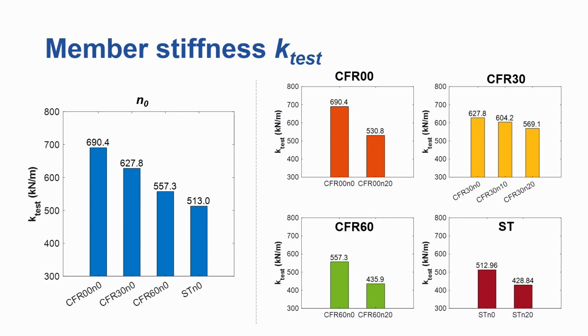And then for a given member type, we noticed that as the axial load level increased, we saw a reduction in the second stiffness. That was quite significant in certain members, indicating that the second stiffness was sensitive to the axial load level.